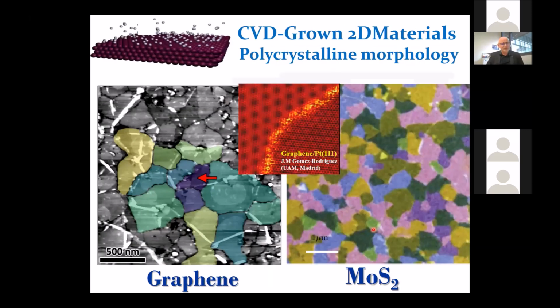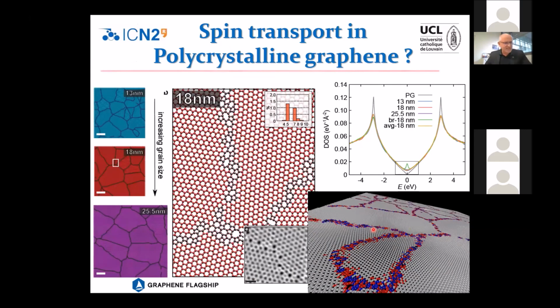But those materials, those CVD grown two-dimensional materials, are not as clean as the ones we know. They have this polycrystalline structure with a lot of defects and grain boundaries. And this was actually one of our major concerns, to which extent these morphologies could impact the spin diffusion lengths, the upper limit of spin information transfer. So we had specific activity during the past years.